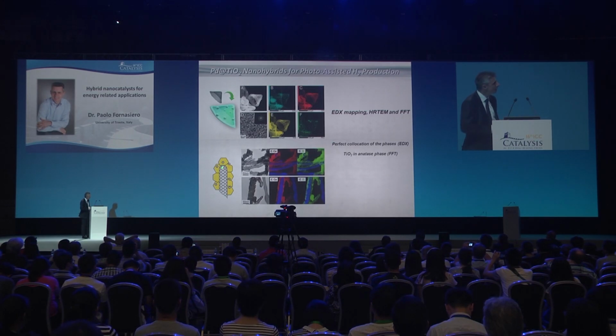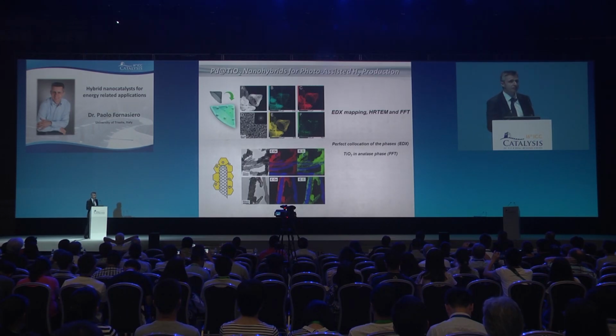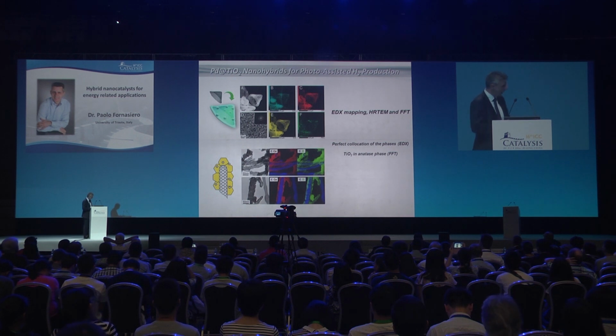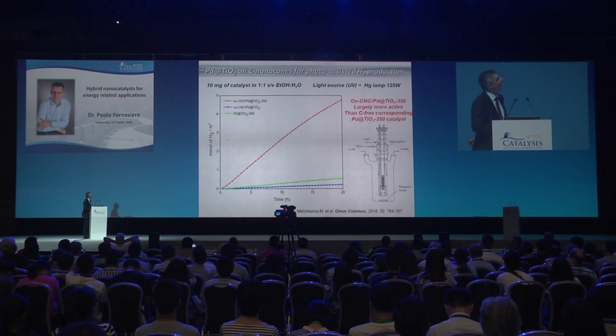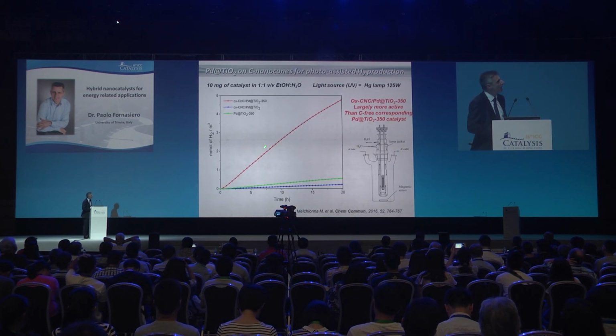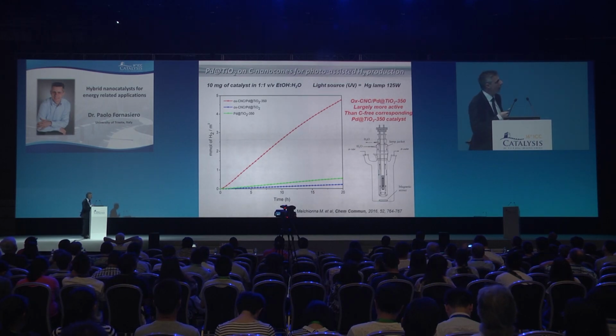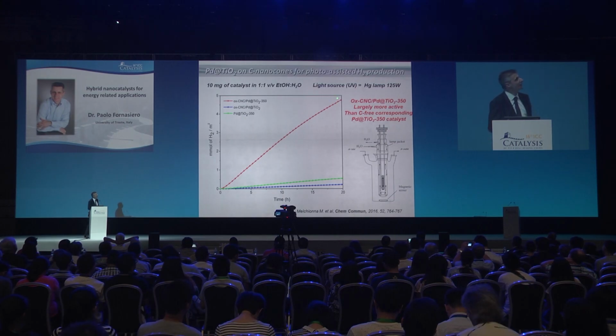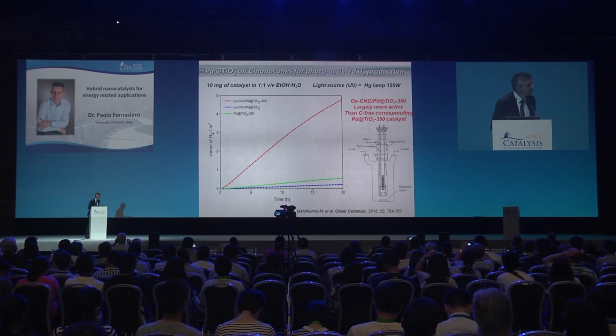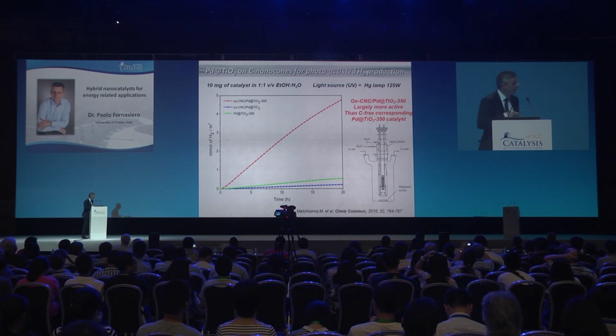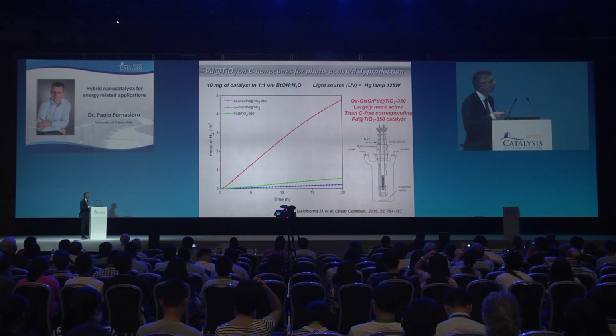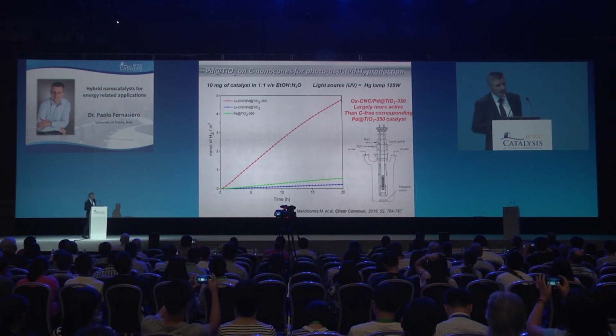palladium, titanium, oxygen, and carbon. And this can be extended to many other fascinating structures: carbon nanostars, nanohorns, and so on and so forth. And really, the amount of hydrogen you can get from this hybrid material is significantly higher with respect to the single components, especially when you compare this in terms of surface area of these materials.